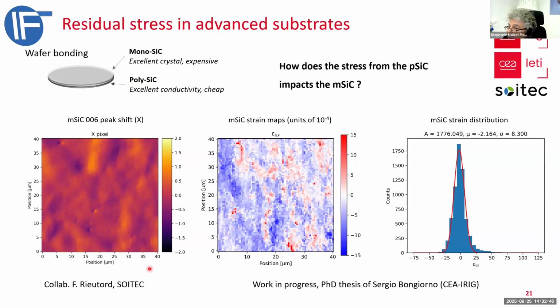What can we obtain? In this example, this is wafer bonding. You stick 2 materials and you want to probe if this poly SiC is changing the mechanical or the structural properties of the top layer, mono single crystal SiC. Then you can analyze the data, and this is a map of the strain with such a unit of resolution. The idea of this work is to correlate or not the grains which are underneath. So the grains could explain this strain variation.